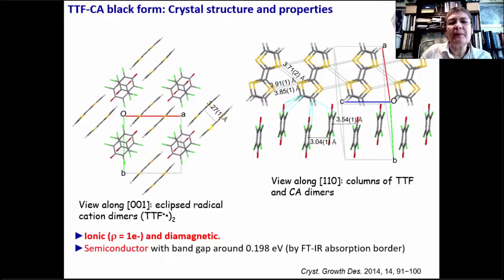So the crystal structure confirmed that this material is ionic, because of the presence of these radical cation dimers, in which two tetrathiafulvalene radical cations form these dimers. So the planes of the molecules are very close together, and there is a sigma bond between their orbitals there. Then the stacks of the electron acceptor chloranil were also dimerized. So there is a longer distance and a shorter distance between the molecular planes, and that also indicates the presence of radical anions. So it was possible to solve this structure and confirm that it's an ionic material.